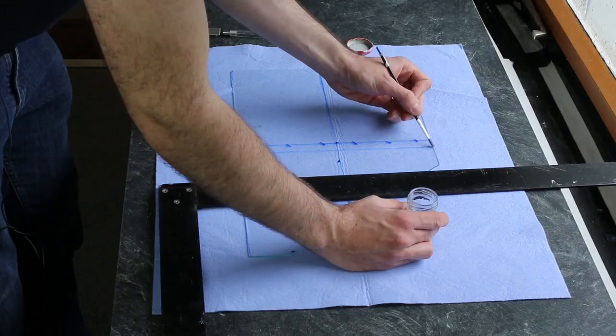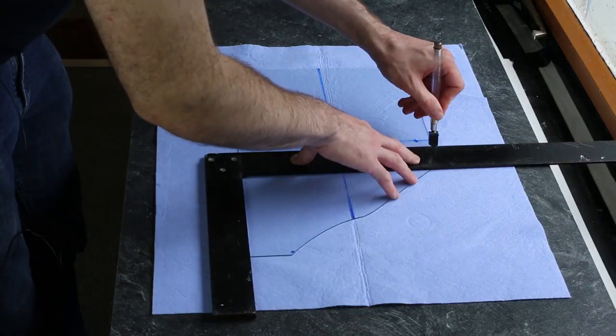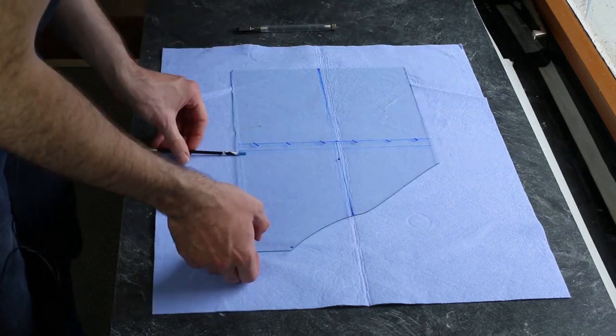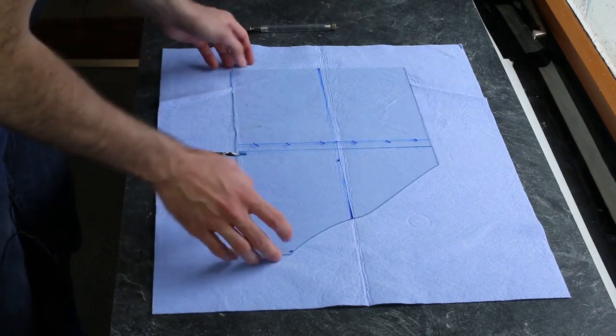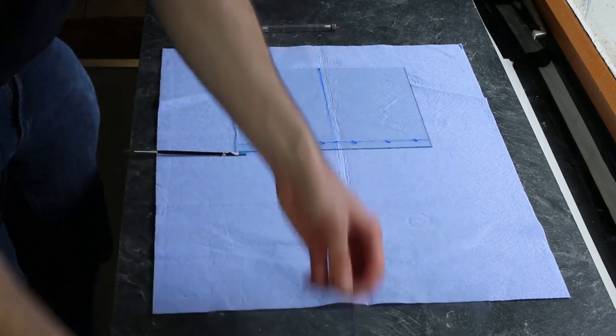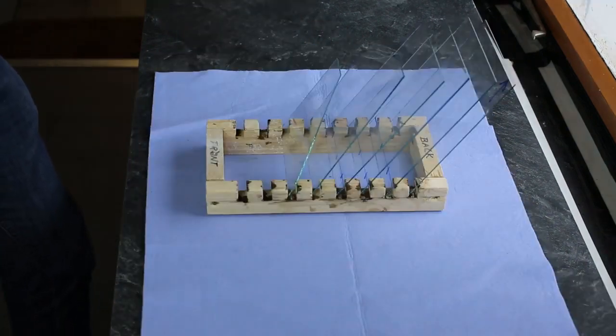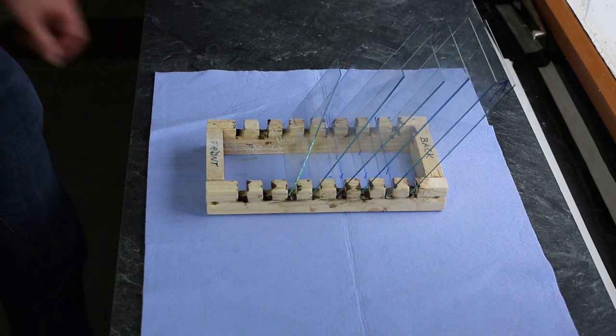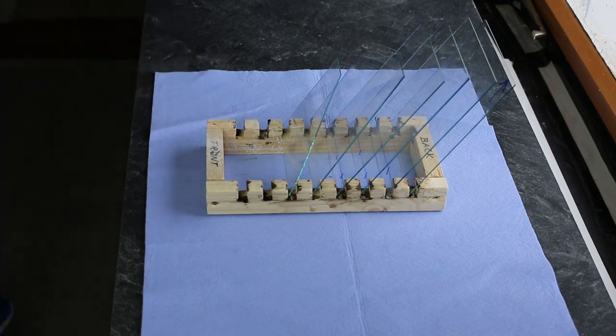Once all the plates are cut, I check them for imperfections or big scratches. These are most easily observed by shining through the glass with a red LED light. Don't throw away scratched glass plates. They can still be used as cover plates later on. About 30% of the glass you buy won't be good enough for making holograms. On a side note, you always want to work with the thickest glass still acceptable for your project. Thicker glass is easier to handle and performs better later on in the process.